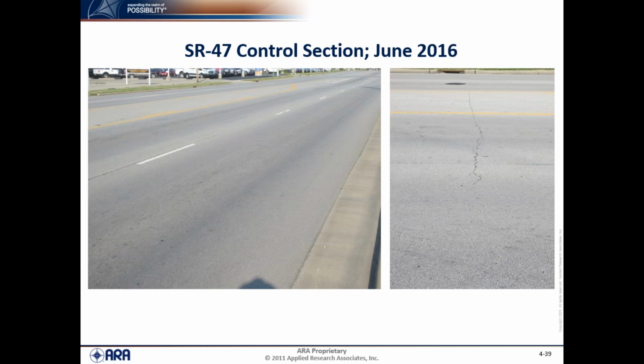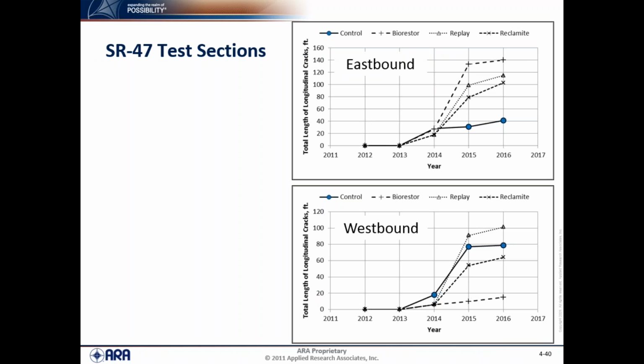Now moving to State Route 47, the control in June 2016. Again, this is the 4-lane undivided with a left turn lane, and in some areas with right turn lanes. This now shows the eastbound versus westbound on State Route 47, and this is basically total length of longitudinal cracking. The length of longitudinal cracking is relatively small. It's not like we were seeing close to 1,000 feet in some of the other sections. It's generally less than 100 feet within the total test section. So it's not a lot.